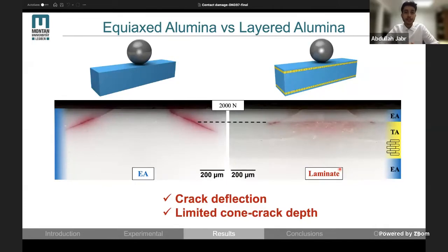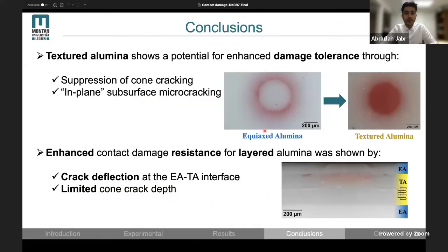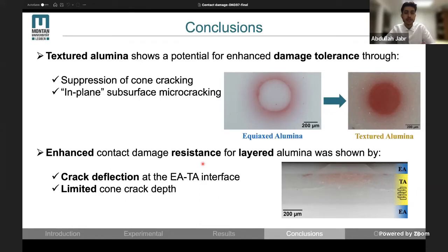What have we achieved by the layered design? Comparing layered alumina to equiaxed alumina, in equiaxed alumina the cone crack extends under loading without any hindrance. Meanwhile, in layered alumina, the cone crack is deflected at the internal textured layer and remains limited in depth. At this point I can answer my two main questions. For the effect of texturing, we saw that texturing changes the damage behavior from classical Hertzian concentrated cone cracking to distributed subsurface shear faulting or micro-cracking, giving us some sort of quasi-plasticity. For our layered alumina design, it shows its ability in deflecting propagating cone cracks, thereby limiting their depth regardless of the applied load.